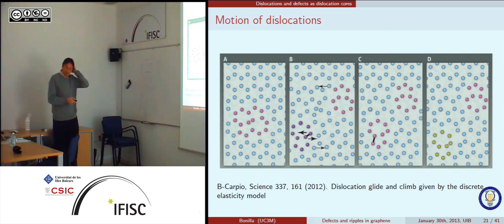So this is something that we did with our discrete model. So you have separated these two pentagon, heptagon defects. Of course, we put the Burgers vector in the x direction because we wanted to use the known solution of elasticity, which is simpler. Now these two rotate and they move like this. And now if we artificially knock off these two and run the model, we see a climb motion. These ones, instead of moving in the x direction, they move in the y direction.